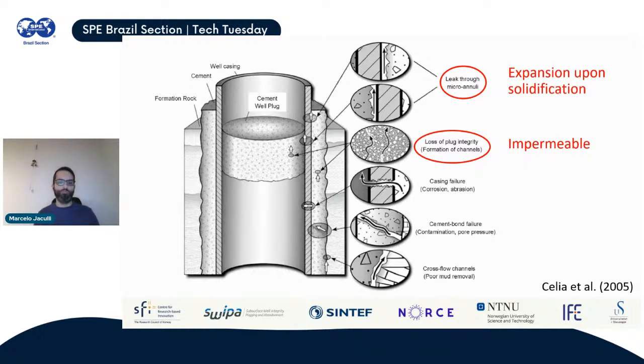The idea of using a metal plug, and in particular bismuth, is because of two characteristics mostly. The problem with the microannuli is that if you are able to close it, then it becomes a smaller issue. Bismuth has a very unique characteristic: the capability of expanding upon solidification. After the alloy is melted downhole and you let it solidify, it starts expanding. Due to the expansion, you create a better seal with the pipe inner wall, at least that's the idea, so you will be dealing with the microannuli. And by being a metal plug, you also have the benefit of a metal being virtually impermeable, so you are not expecting any leakage through the plug. You are expecting leakage through the microannuli, which may or may not be closed depending on how much expansion you get.